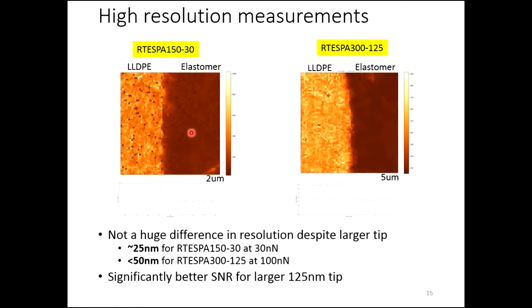And finally, in terms of resolution, for these well-controlled probes, they come in two flavors, either one with a 30 nanometer radius or one with a 125 nanometer radius. We had a blend here with two blocks that were cryotomed together. We could look at the interface to probe the resolution of the probes, how well the measurement's doing. We can see that in terms of measuring the interface, on the 30 nanometer and the 125 nanometer, there actually wasn't a huge difference in resolution, despite the fact that we had very different tip sizes. In fact, the 125 nanometer tip certainly also has better signal to noise. Again, not surprising. It's more contact area, more penetration into the sample.